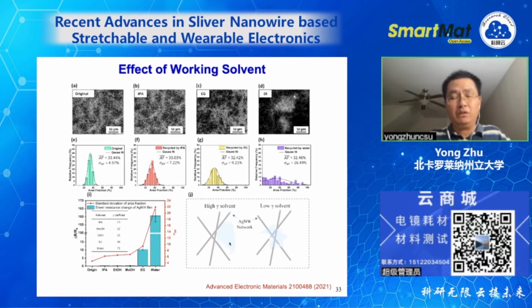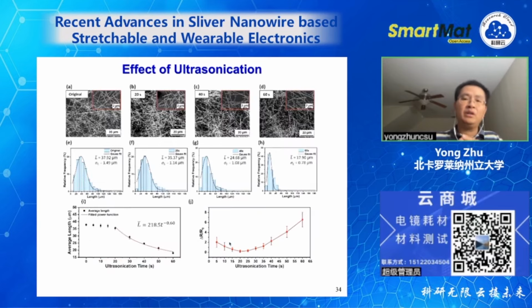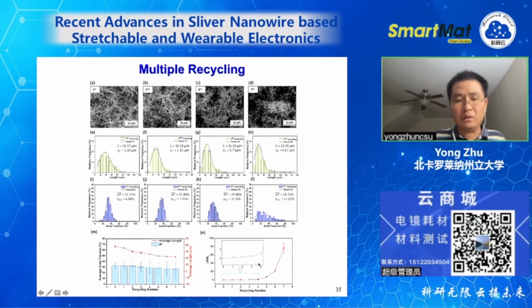And then ultrasonication is also important. If you do it too long, you're going to shorten the nanowires. That's a well-known phenomenon. But if you do it too little, the purpose of ultrasonication is to disperse, to form a uniform distribution. So we have to find a trade-off. If it's too short, it's not good. If it's too long, breaking the nanowires is also not good. This is reflected in the resistance. So we have to find an optimized time. For the power we use, it is about 20 seconds.